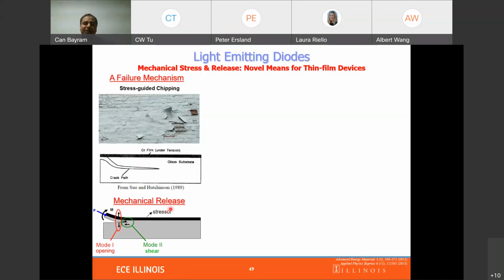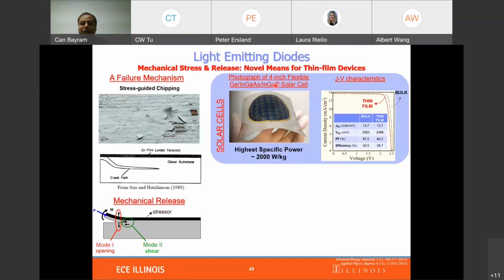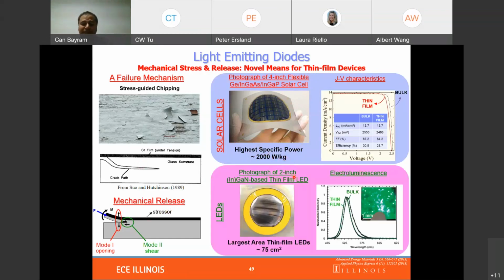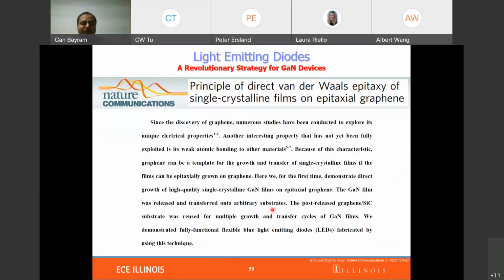So the goal here is, can we create a structure where we can really control these opening modes and the propagation modes of these stress layers? This has been done, as you can see here, for 4-inch solar cells, where we demonstrated high specific power solar cells when it was published, as well as on 2-inch thin film LEDs. What you may notice when you look at nitride LEDs is that there are strict lines here, and this is because of the mode 3 effects. So the question is, can we remove these stress patterns, or can we even make these devices thinner? The solution comes from finding a perfect mechanical release structure,